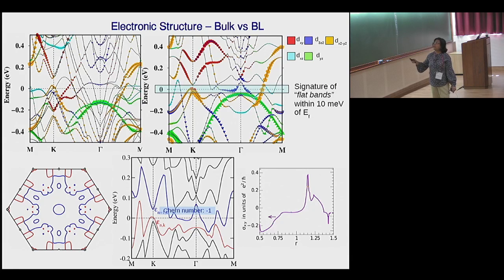And in the bilayer limit, this flat band shows up at the Fermi level, within plus minus 10 meV of the Fermi level. And if one computes the Chern number of these flattish bands close to the Fermi level, it shows a non-trivial Chern number. So therefore, there is a very good possibility it will be a Chern metal. And the anomalous response of such a Chern metal, as calculated, is also non-zero. This non-zero value can be obtained for a large range of the R parameter, which is basically the ratio between the big triangle and the small triangle. So this kind of Chern metallic behavior will be a robust feature in these bilayers of this Kagome compound of iron, or maybe even allied compounds.